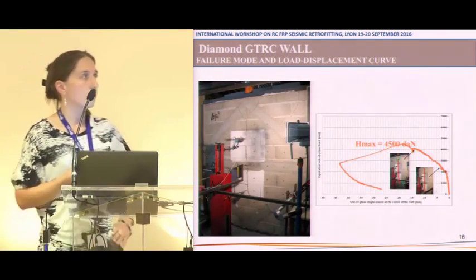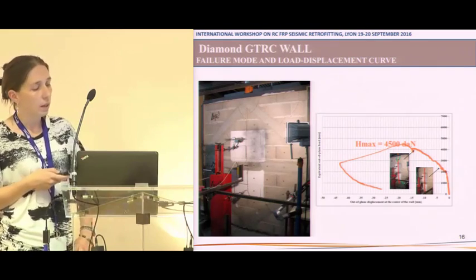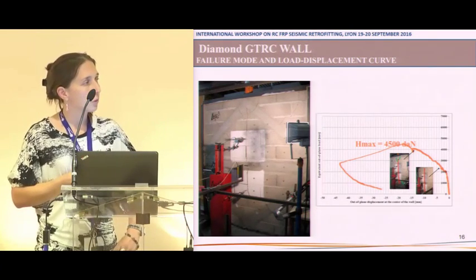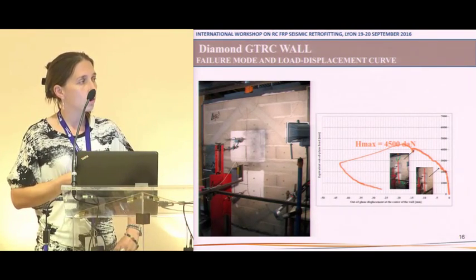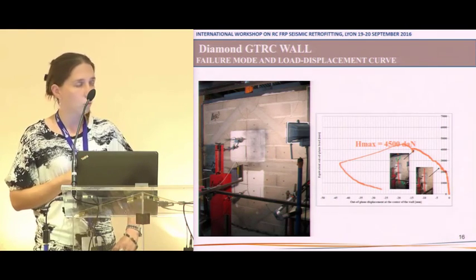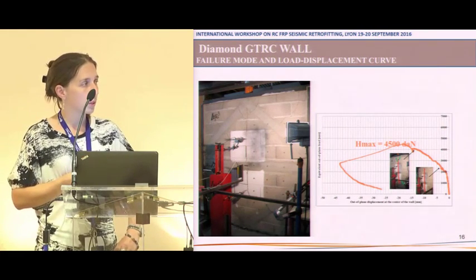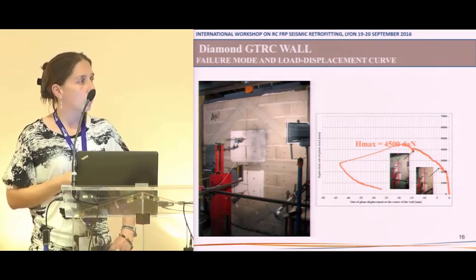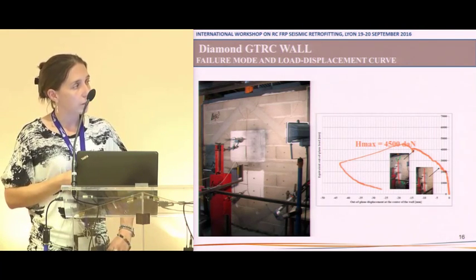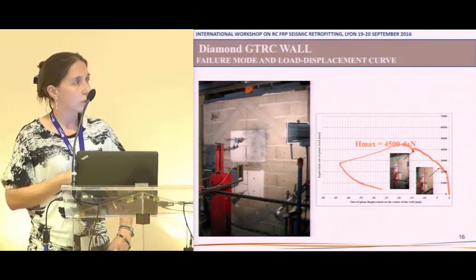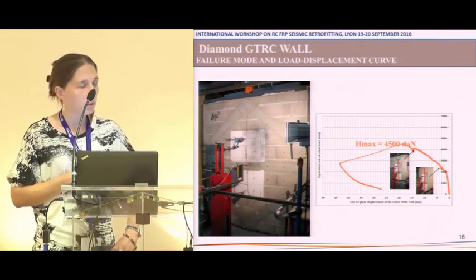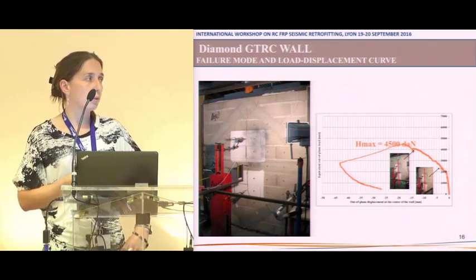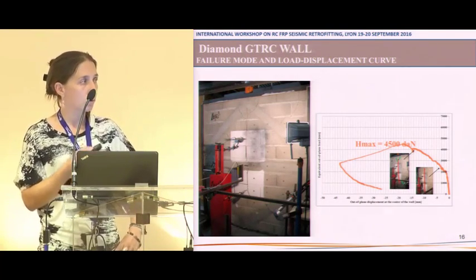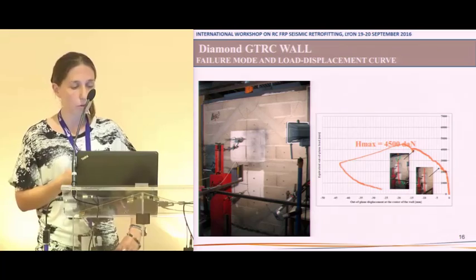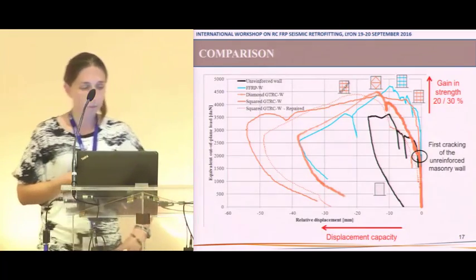In the last case, the diamond GTRC wall, we can see that the first vertical cracking, around 2000 decanewton, appears first as in the unreinforced wall, and then we have inclined cracks that are again contained by the TRC materials. The maximum load is the same as for the other reinforced configuration.